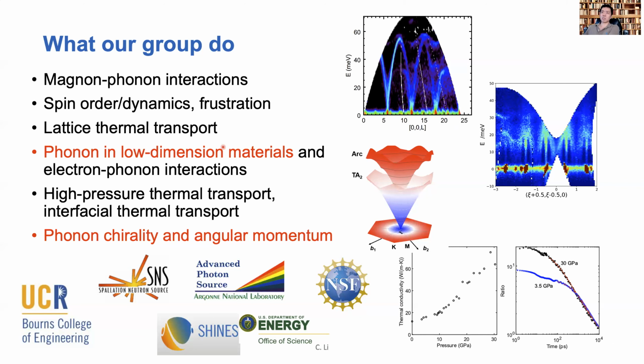We also work with lattice thermal transport by both neutron scattering and inelastic X-ray scattering, but we also do some high pressure thermal transport measurements. This is in collaboration with a colleague also at Riverside. We use time domain thermoreflectance and time domain MOKE, which is the magneto-optical Kerr effect, by looking at thermal transport under pressure. This part of the work is done in diamond anvil cells.